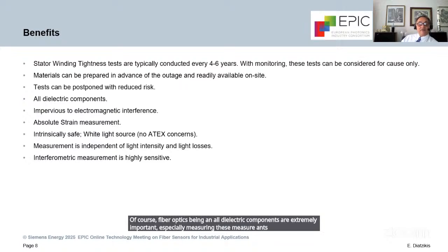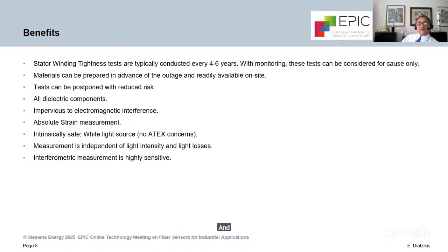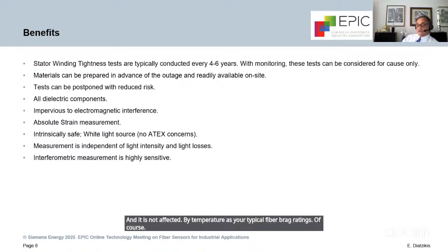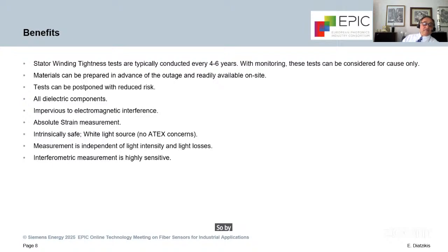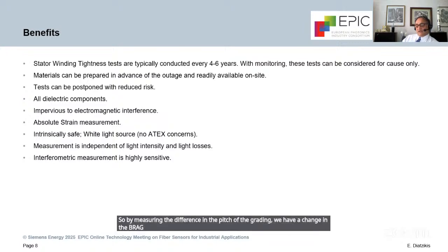especially for measuring these measurands inside the generator, because they're impervious to electromagnetic interference. For this particular sensor technology, it is an absolute strain measurement, and it is not affected by temperature as your typical fiber Bragg gratings are. Of course, we know the Bragg condition is twice the effective index and the pitch of the grating. So by measuring the difference in the pitch of the grating, we have a change in the Bragg condition, in the Bragg wavelength.